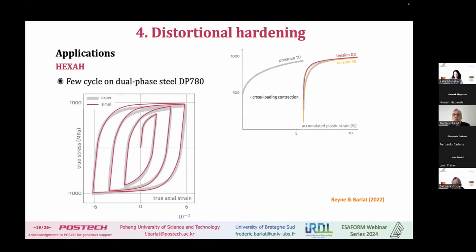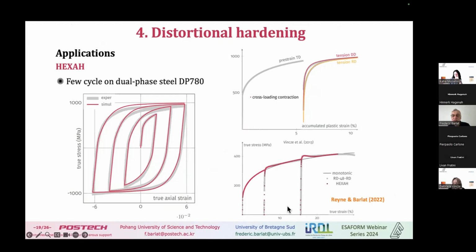Now, if we do pre-strain, like from tension in a different direction, we see we get a good agreement again. And here, this is a case where we have overshooting. We see that we are able to represent overshooting well. And also, those are examples where coefficients were calculated so-called manually. Because we know the coefficients, we know what they represent physically, and therefore we are able to calculate them, I mean, to tune them and to find a good agreement.